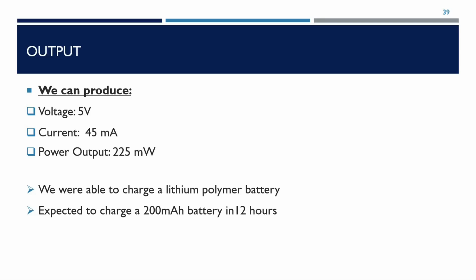The result of our final product, we can produce 5 volts at 45 milliamps leading to a power output of 225 milliwatts. Thus, we were able to charge a lithium polymer battery, and the expected charge time of a 200 milliamp hour battery is approximately 12 hours.